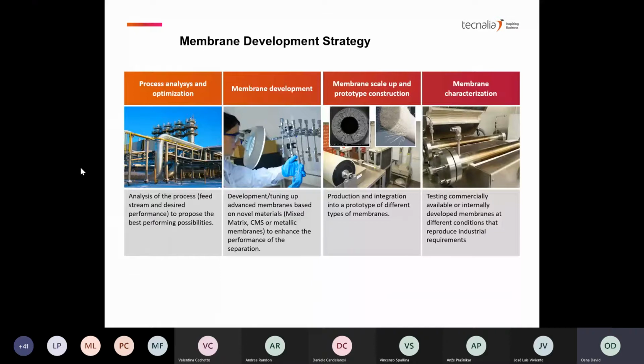So therefore, when we make a membrane development strategy, we first start with process analysis and optimization. Looking at the application where we want to use the membranes, we define the target values for the membranes in terms of permeability and selectivity. Then we develop the membrane with the asymmetric structure and hollow fiber geometry, preferably as I described before. And we test the membrane, we scale it up, and we try to reach a commercial membrane.